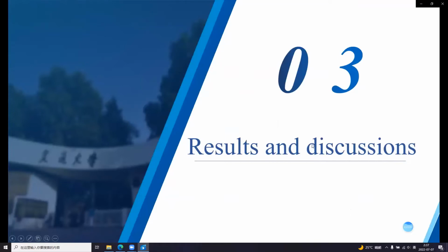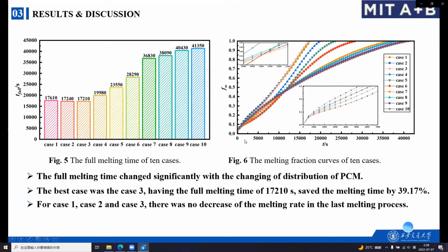The third part is the numerical calculation results and discussions. The first picture shows the full melting time of 10 cases, and case 6 was the basic case, whose full melting time was 28,290 seconds. The best case was case 3, having a full melting time of 17,210 seconds, which saved the melting time by 39.17%. And as predicted before, the cases with more PCM in the lower part all prolonged the full melting time.